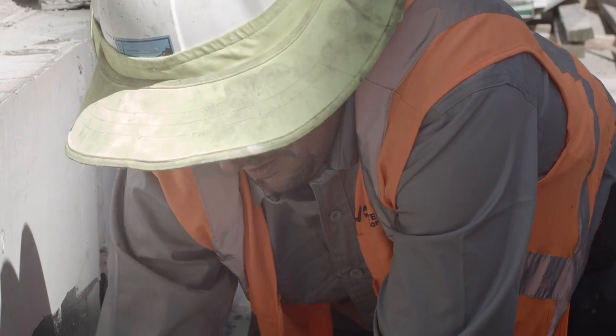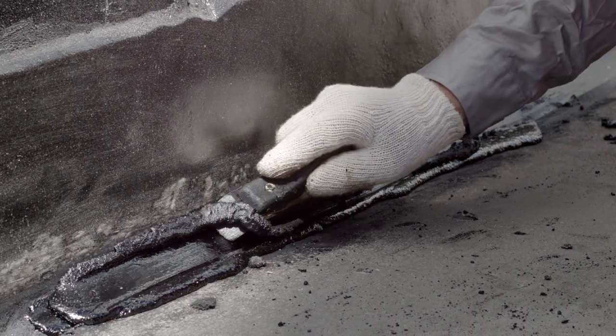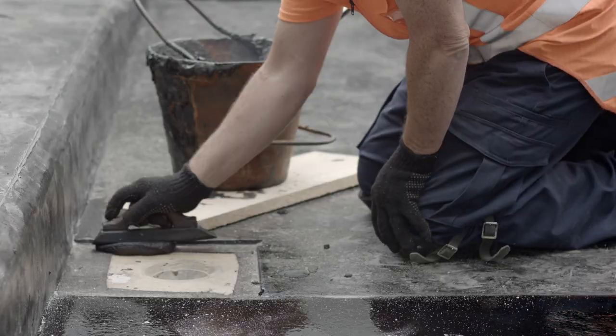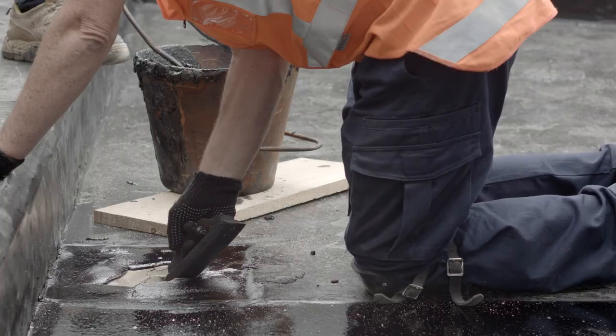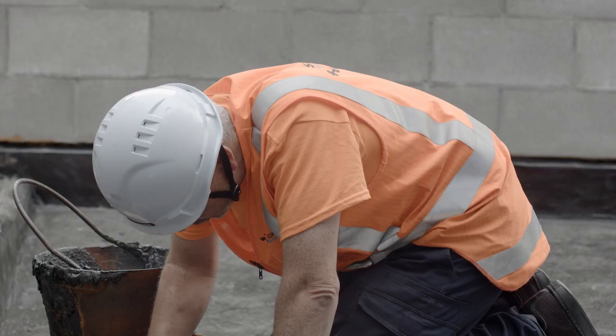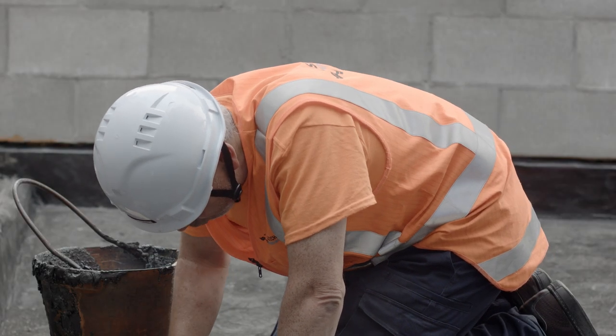Sand is applied to the product while it is hot. A mastic asphalt fillet is applied to reinforce the horizontal and vertical layer. Outlets should be cast bronze metal type — they should be primed, then two layers of mastic asphalt should be applied. Mastic asphalt should not be applied to PVC pipes.